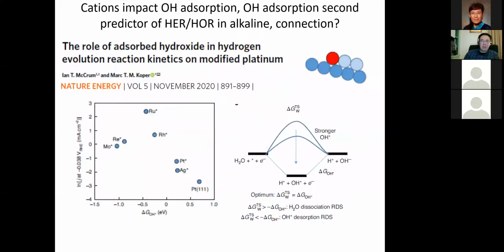But Ian, once he joined Marc's group, brought those two thoughts together, and they just had a Nature Energy paper come out late last year, where again, they did a nice, careful set of experiments where they just changed the presence of another metal atom at a step of platinum. And they showed a nice volcano between the current density and the hydroxide binding. And then they combined that with DFT calculations that did have activation barriers, and essentially explained this as the rate determining step.